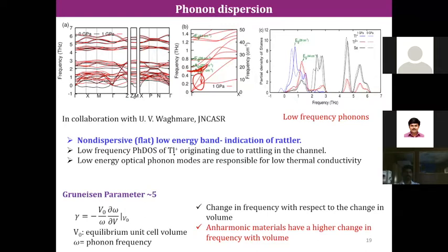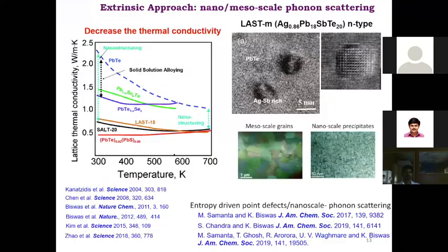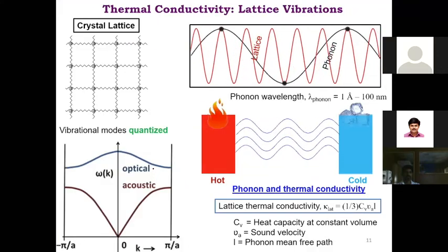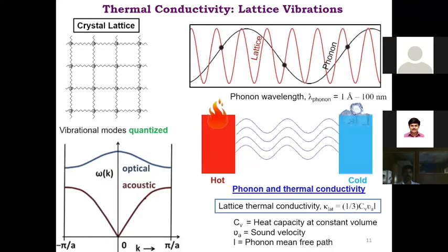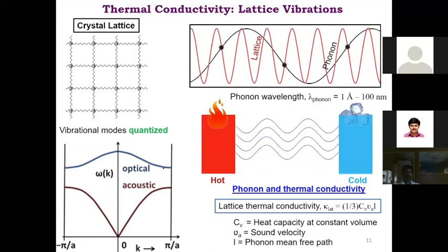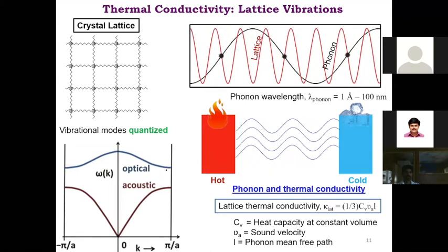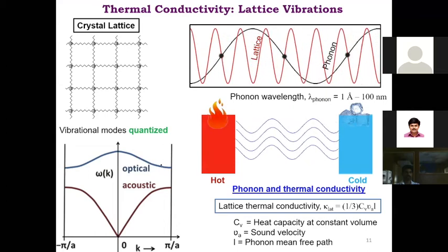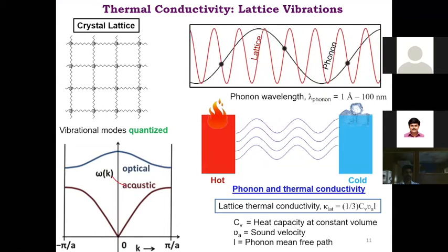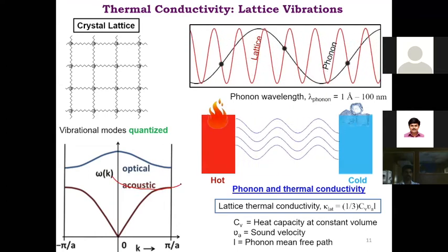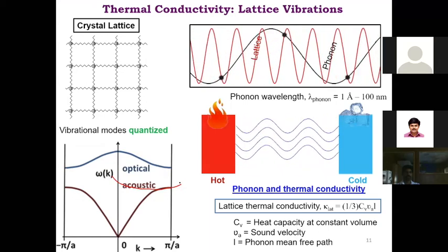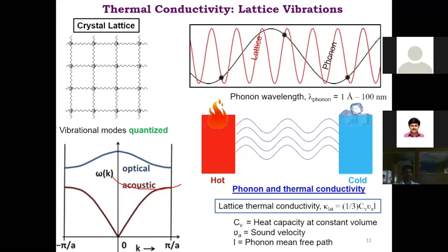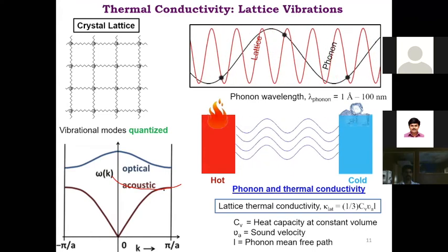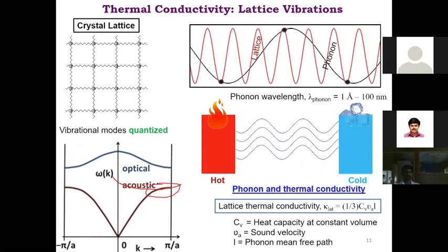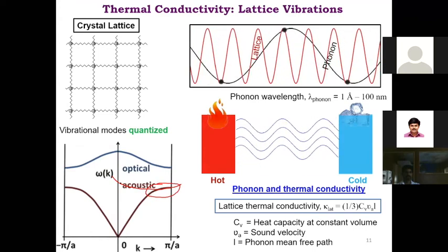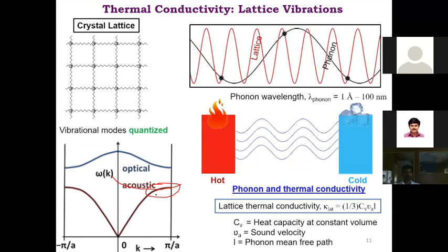Okay, so what I mean here, as the slide has not changed, I'll go back here. So I told you this acoustic mode is carrying the heat, and in a normal semiconductor you have these optical modes. What we have done is we lowered the frequency of these optical modes by slow vibration or rattling of thallium, and this optical and acoustic coupling is happening. And this optical acoustic hybridization gives rise to ultra low thermal conductivity here. And this low optical mode is coming from the thallium rattler.